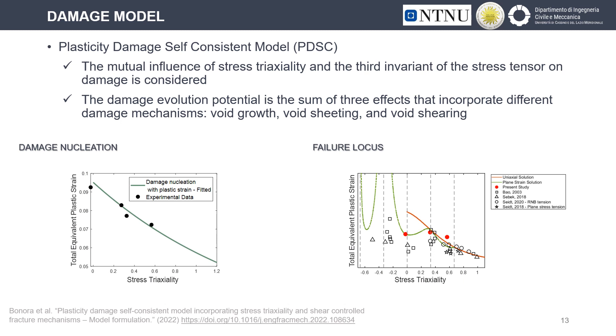The model requires the identification of a damage nucleation law, which we fitted on the experimental results obtained with the SEM in-situ techniques, and of a failure locus. We compared the fracture response of our alloy to other experimental data in the literature, and found that our alloy has a comparable tensile response to other literature data, but has a higher resistance under shear conditions.